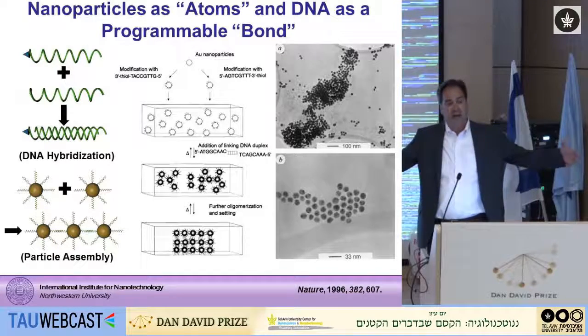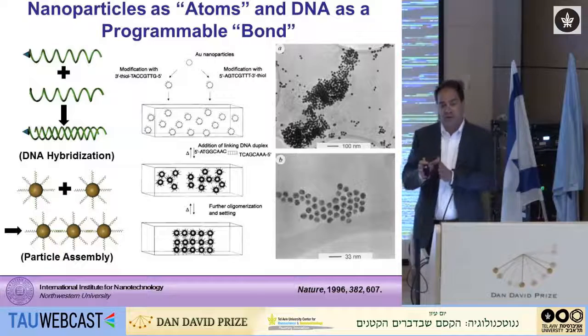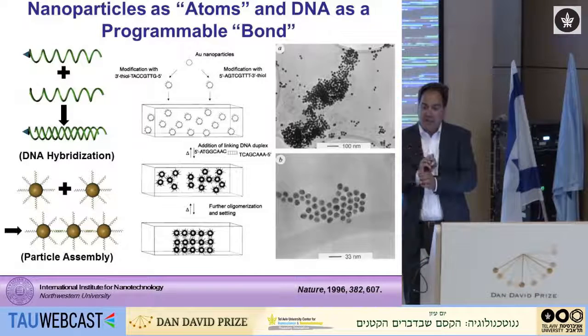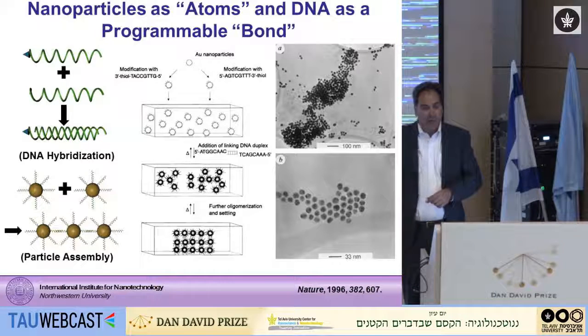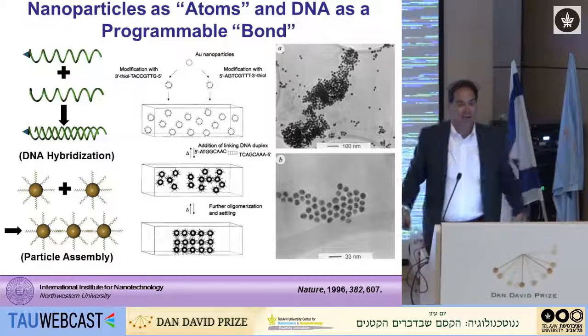And we did that. And we knew we did that because if we took these systems and we heated them, they would melt exactly at the melting temperature of the duplex interconnects holding them together. And it was a highly reversible process, and you could watch the raveling and unraveling of the DNA based upon the plasmonic properties of the particles. That actually led us down the path of developing new types of diagnostic tools. And then these were the not-so-impressive structures that we had generated.